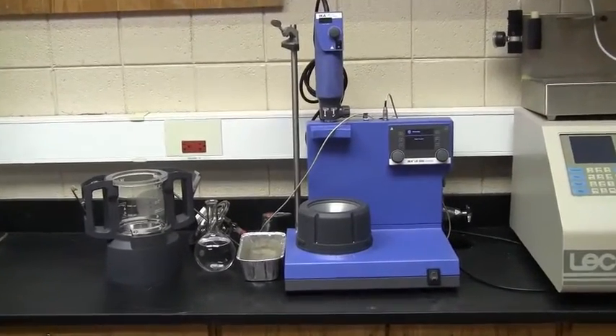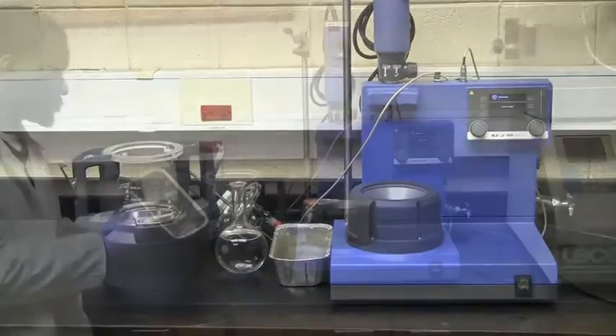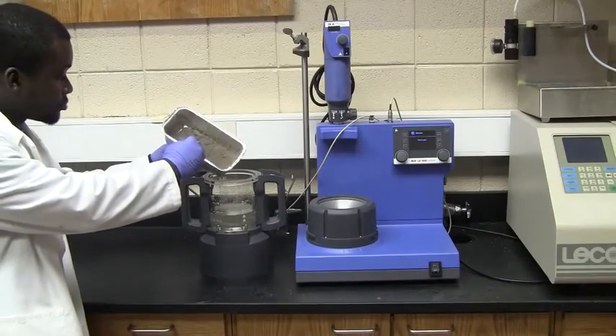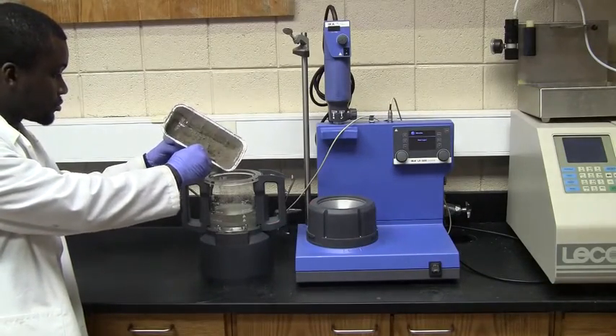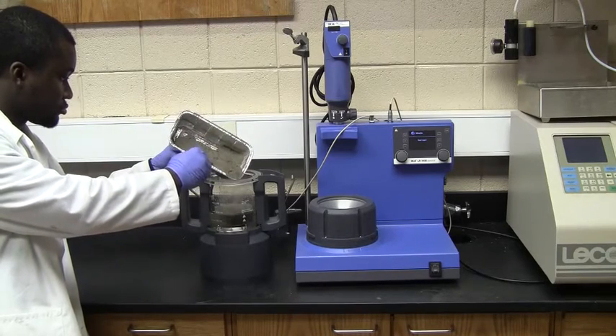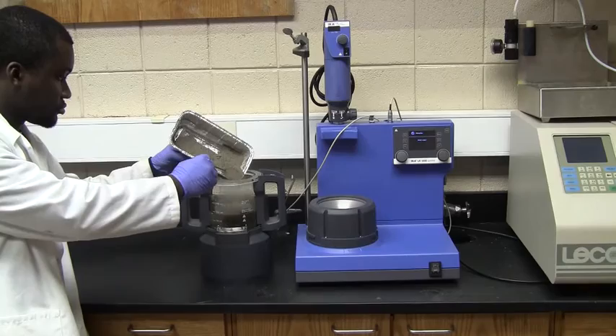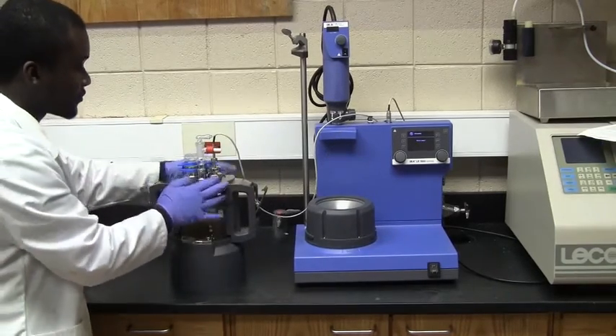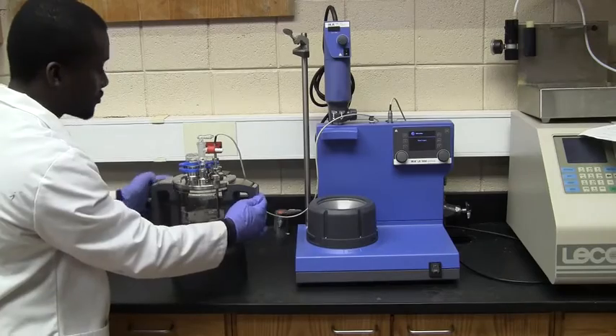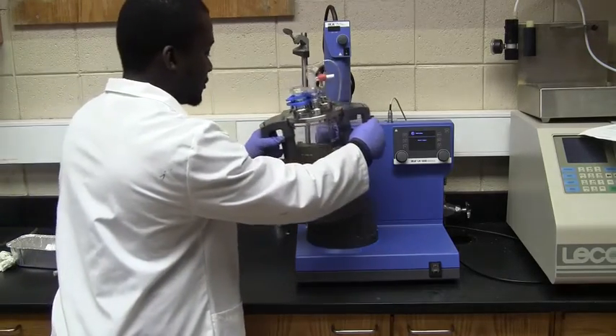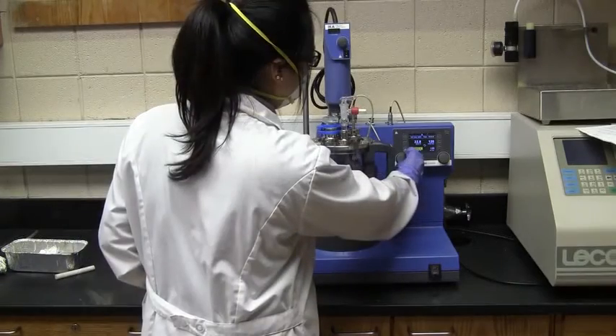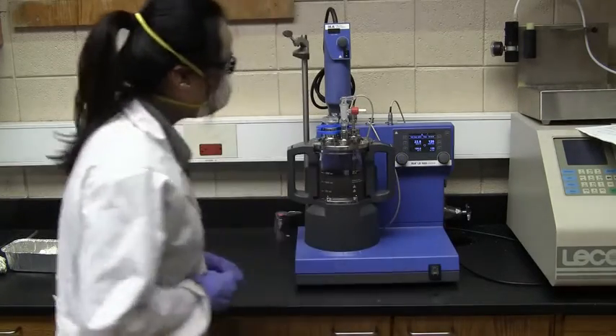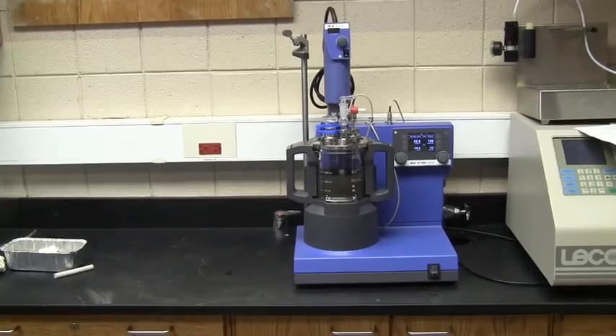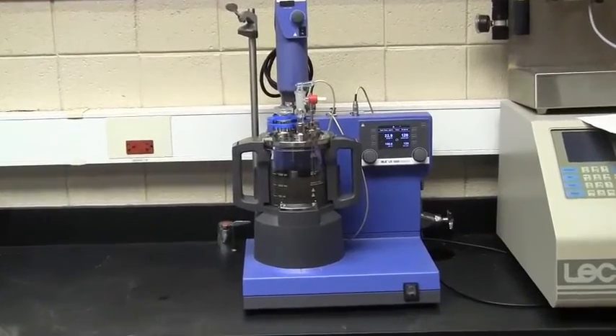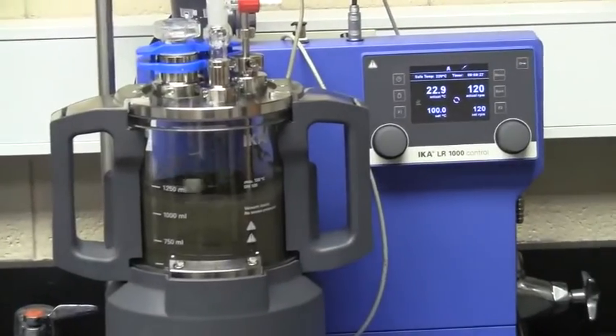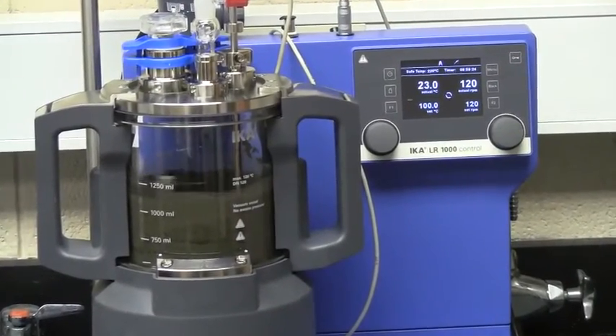Carefully add the prepared 6 molar sulfuric acid into the vessel, and then add the fly ash sample into the sulfuric acid with a solid to liquid ratio of 1:4. The lid must be locked during the reaction. Slowly increase the speed of the stirrer to 120 RPM. After observing the solid to liquid mixture is well mixed, set the temperature at 100 degrees Celsius. Operate this experiment for 10 hours.